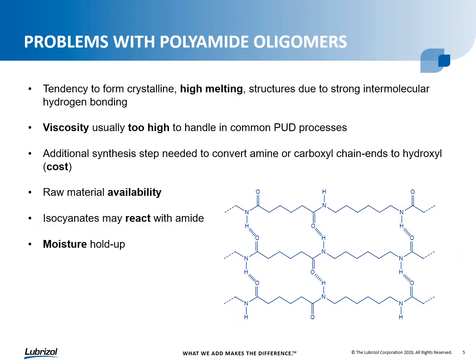So I mentioned on the last slide that there was previously no commercial availability of polyamide polyols to use as a viable soft segment in making polyurethane dispersions. And part of that has to do with various problems associated with working with these polyamide oligomers. Some of these being that they have a tendency to form crystalline, high melting structures due to a high degree of hydrogen bonding. And we talked about how when you react that soft segment or the polyol with the isocyanate, it's fairly viscous in nature. And so, even more so, the viscosity is usually too high to handle in a common PUD process.